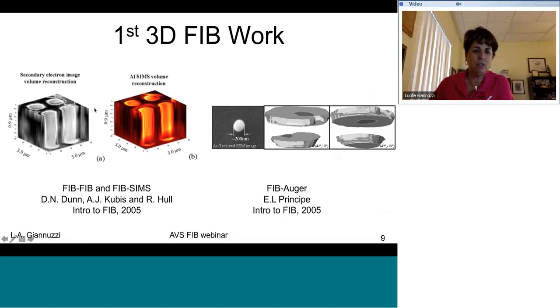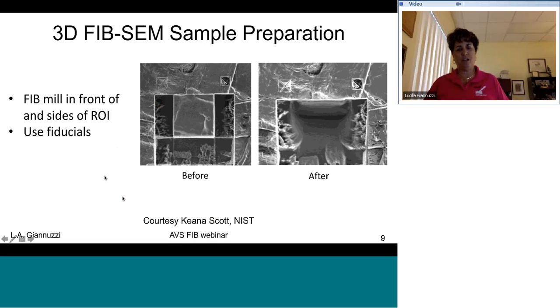So Robert Hull and co-workers showed that you could take a slice, image with a FIB, take another slice, image with a FIB, and at the same time collect SIMS information to create a 3D volume of material. And Ed Principe showed that you can collect Auger information on each of these FIB slices, collecting 3D information as well. Note that because we're FIB imaging, FIB sectioning and then FIB imaging, the 3D FIB work is destructive. So once that sample's gone, it's gone. There's no way to come back and look at it.